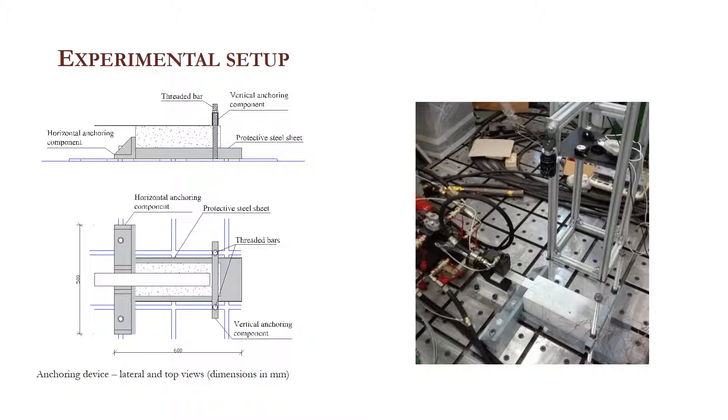Composite systems are widely used in the structural rehabilitation of concrete reconstructions. Indeed, the plating technique of beams with fiber-reinforced polymer represents a quick and optimal intervention with respect to traditional ones. The failure of these composite systems usually occurs due to the FRP debonding, which corresponds to a mode-II fracture of concrete specimens.